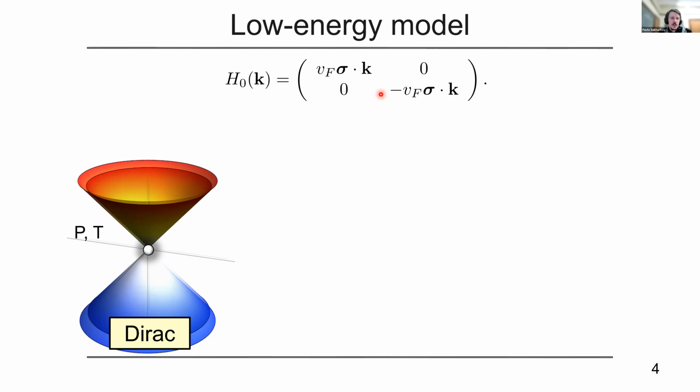The energy spectrum of such a Hamiltonian is very simple. It's just a single Dirac node. It preserves both inversion (parity) symmetry and time reversal symmetry. The node is doubly degenerate. One might say that in Dirac metals these bands can hybridize and open a gap, but this doesn't happen because there is usually some crystal symmetry that protects these nodes from hybridization.